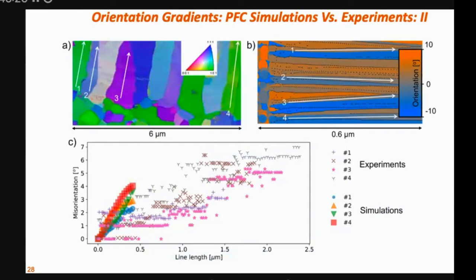If we look at the experiments on the left, we track the orientation change within the single grain as shown by the arrows here. And that's plotted here. On the bottom is the line length. These white lines here. And this is the misorientation. And on the right top frame is our simulation showing these line lengths in white tracking through individual crystals and showing a misorientation change as you track through individual crystals.